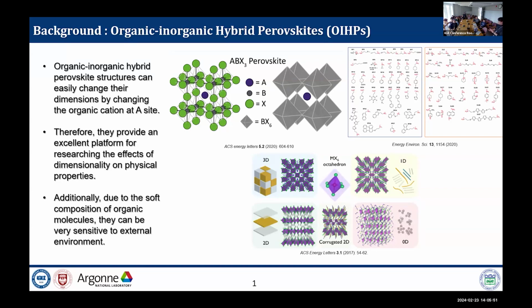Particularly within the organic-inorganic hybrid perovskite, it is easy to modify the dimensionality of the inorganic octahedra by changing the organic cation at the A site. So it is a great playground for exploring changes in physical property due to dimensionality. Also, due to the soft composition of the organic molecules, organic-inorganic hybrid perovskites have many structural phase transitions with external conditions such as temperature. So there is a possibility that they can be very sensitive to external pressure. Specifically, the 3D OIHP exhibits an outstanding photovoltaic effect, 2D has some unusual magnetic or electric properties, and 1D and 0D showcase quantum dots or light emitting diodes.